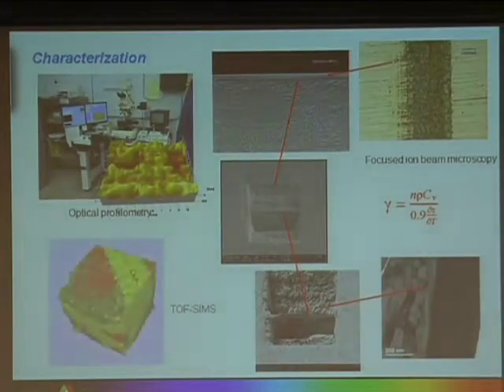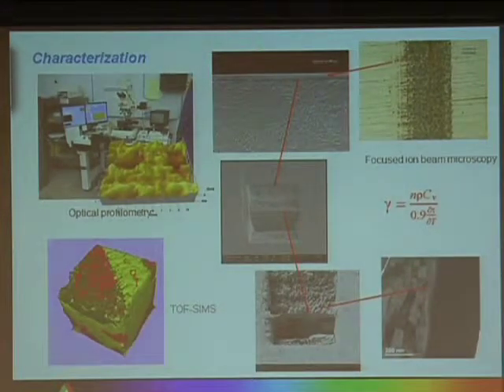Characterization techniques are shown here. We do quite a bit of work using an optical characterization system that we can use to measure and quantify the thickness of the tribo films that are formed, as well as the fact that these are not really uniform films. They are very heterogeneous on the surface, and the thickness varies considerably. We use this quite a bit initially to look at the films, and then we're starting to use a focused ion beam technique to look at the chemical composition and microstructure of the films.